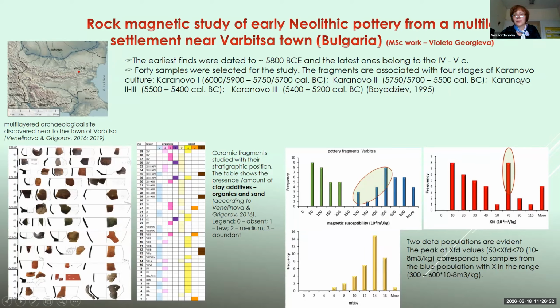And these are the 4 stages of the Neolithic culture Karanovo, which were included in the collection of ceramics from the site. Here you can see the fragments which were included in the study. And one important characteristic of these materials is that they contain different amount of organics and sand as additions in the ceramic paste. So these additions were quantified as a range from 0 to 3 in increasing amount.